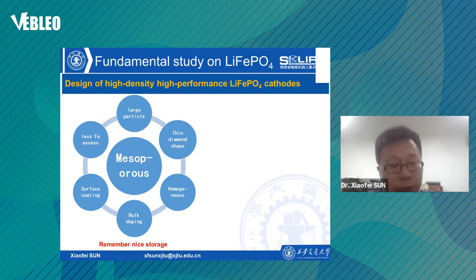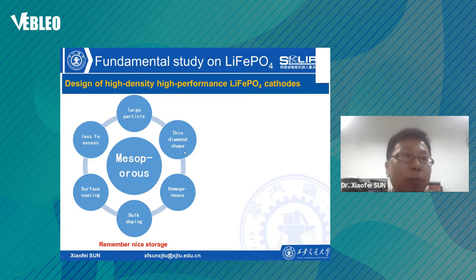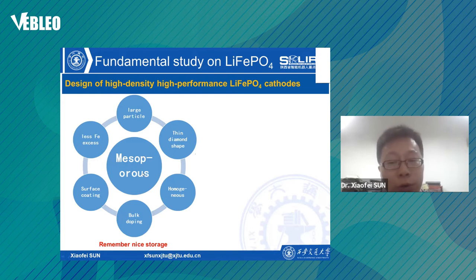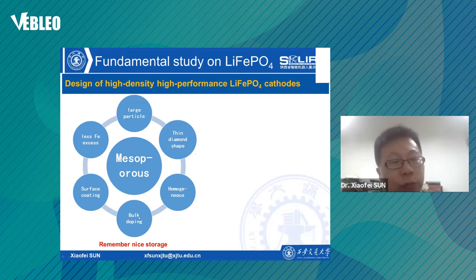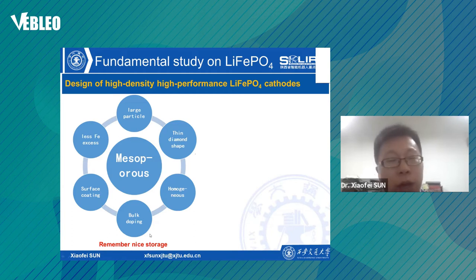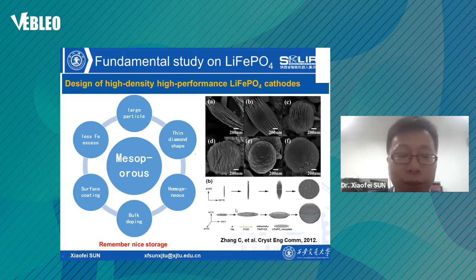Based on the above findings, we proposed some principles for designing high-performance large-particle phosphate cathode materials. The large secondary particles are homogeneously stacked by small-shaped primary particles to form a mesoporous structure, and the electrochemical performance could be further improved by combining surface coating and bulk doping as widely used in literature. In addition, iron excess should be carefully controlled, and storage conditions should be managed to avoid the influence of water and oxygen. This idea has been realized by Zhang et al., and the practical morphology of this design looks like this.